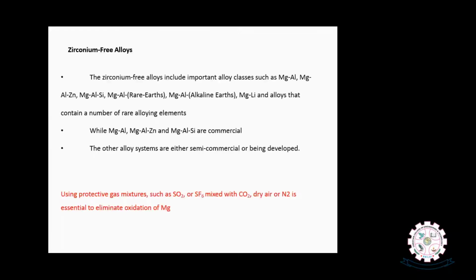Now we'll see quickly different processing routes which can be adopted to develop components using magnesium alloys. When it comes to casting, basically we use casting to produce base alloys of magnesium, sometimes directly components of magnesium also. There are several alloying elements we add to magnesium to develop novel magnesium alloys. For example, the classification of magnesium alloys can be done by considering the amount of zirconium. If we have a considerable amount of zirconium, we can specify them as zirconium-containing magnesium alloys. And if we don't have a sufficient amount of zirconium, of course a negligible amount also we count, then we call that zirconium-free alloys.